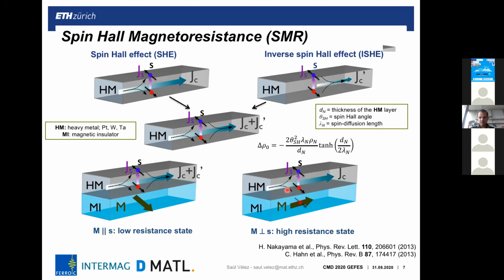Now if you put this material next to a magnetic insulator, you read a different resistance depending on the relative orientation between the spins and the magnetic moments. Because in this configuration, in the first approximation, you could think that there is a reflection and no actual absorption of these spins in the magnetic insulator. But when the configuration is perpendicular, there is an absorption, and thus a reduction of this additional charge current, and this leads to a high resistance state.